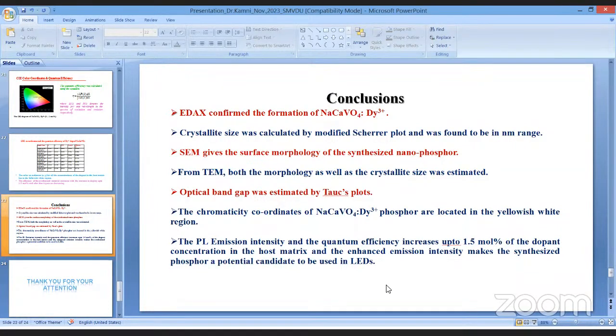So the conclusions: EDX confirmed the formation of our material, which is doped with the dysprosium rare earth, and crystallite size was calculated by using the modified Scherrer plot, and it comes out to be about 41.44 nanometer, which was found to be in the nanometer range. SEM was employed, and it gives us the surface morphology of the synthesized nanophosphors, and TEM was employed to check the particle size. Both the morphology as well as crystallite size were estimated, and were compatible with what we have observed in the XRD pattern.